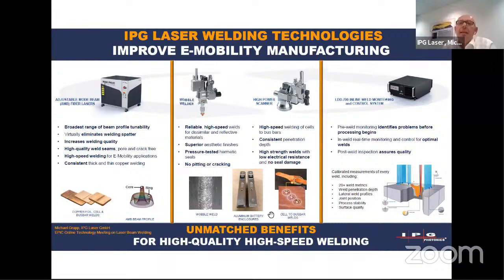The other system, as I already mentioned, to improve and to guarantee the quality of a weld is our inline depth monitoring system, very similar to what Markus from Precitec already presented. We call it our LDD system, a laser depth dynamic system, where we can look into the keyhole, where we can measure the depth of the keyhole, where we can post-weld inspect the weld, or pre-weld find the seam. So this is a multi-tool, one tool for several applications and several measurement tasks. So we have an inline quality assurance tool, which directly gives out the values you measured in time. Next slide, please.